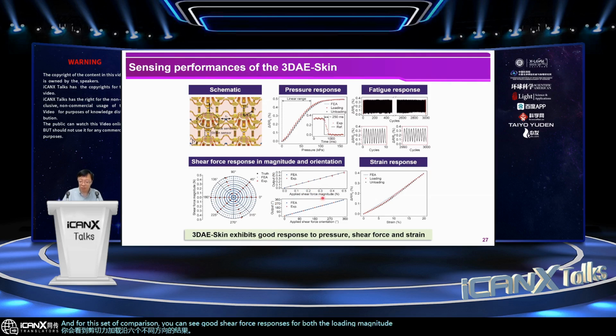From this set of comparison, you can see good shear force responses for both the loading magnitude and the orientation. Also, in terms of the uniaxial stretching, we have tested the cyclic performance after around 10,000 cycles of strain amplitude of 20%. After this cycle experiment, the strain response is still very reliable. So this set of sensing testing shows a very reliable and robust sensing performance.